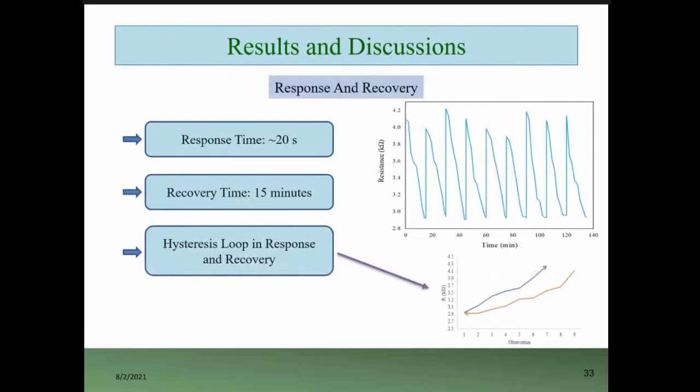After that, I recorded the response and recovery time of my sensor, where I found that when I was increasing the bending angle from 0 to 3 degrees, the sensor was responding quite immediately. For example, the response time was around 20 seconds. But when I let the sensor go back to 0 degree from 3 degrees, it was taking a large time, which is around 15 minutes.